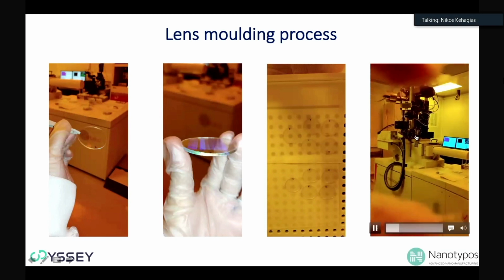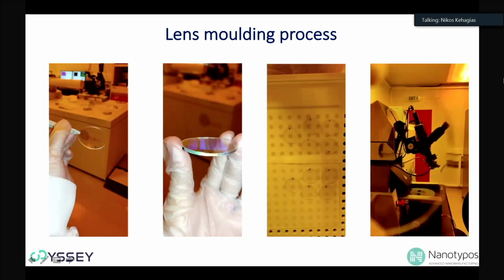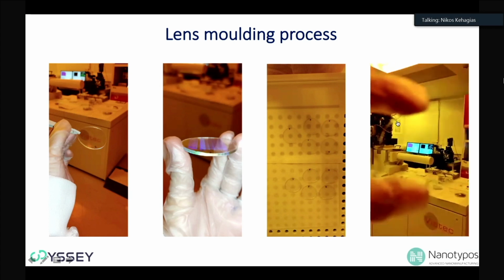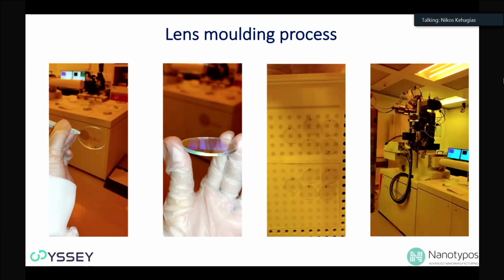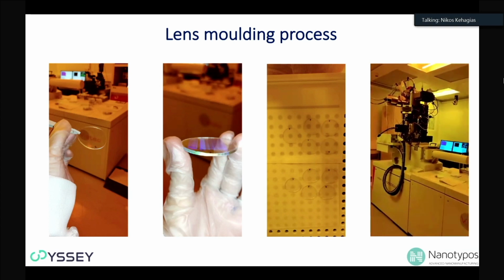So this is just some images of the actual lenses. These are about 4 centimeter wide lenses, fully patterned, very nicely. The transparency is there, planarity is there. We're still continuously working, and within this time frame of the project, we did develop our own materials, which are suitable not only to replicate, but also to meet the standards of the post-processing processes that are required to really fabricate these metasurfaces. And by post-processes, I mean some coating, etching, and developing processes. This material is resistant to some chemicals, heat, and funny enough, it is flexible, so it doesn't break.